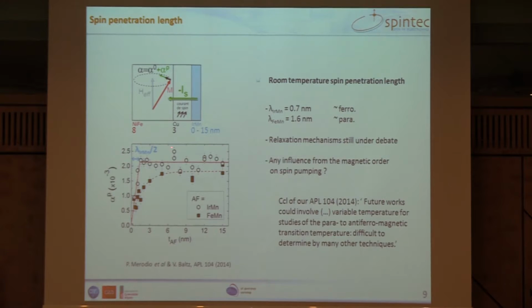So from this data, we can extract a parameter which we think is directly related to the spin penetration depth in our material. So for iridium manganese, we extract typical values of 0.7 nanometers, which is typical for a ferromagnet. And for iron manganese, we get 1.6 nanometer-ish, which is typical for a paramagnet. From this data, we wanted to try to discuss the relaxation mechanisms, because we thought that if you are ferromagnetic-like, the relaxation mechanism is more dephasing-like, and if you are in a paramagnet, you have more contribution from diffusion. But this is actually still under debate.